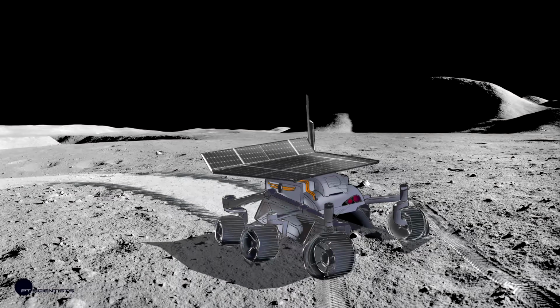Yeah. So one of the ideas that was proposed is this boring lawnmower. But we think of something cool like this one. So the idea is that you have the magnetrons on the bottom side, and while you are driving, you're actually irradiating the surface, and this irradiation brings the material to about 1,200 degrees Celsius in a very quick time. And this starts the melting process so that you get the very nice coating. And because we're using microwave, this is a very power efficient way of doing that.